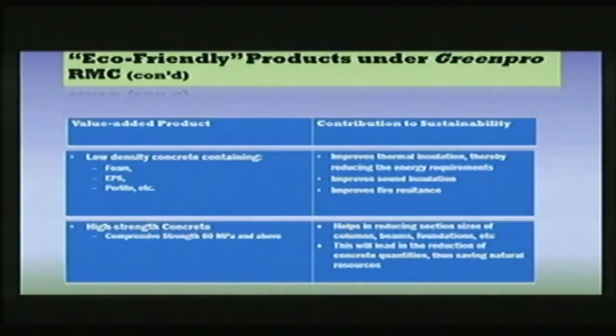High strength concrete, as we already know that as we increase the strength, we can reduce the section sizes, and this is what is happening in Mumbai, that in any tall building we are using high strength, high performance concrete. By increasing the grade of the concrete from M40 to M80, M90, you reduce section as well as reinforcement. And most of the builders are now adopting this. And ultimately it leads to the use of a lower amount of concrete, and we save a lot of resources.